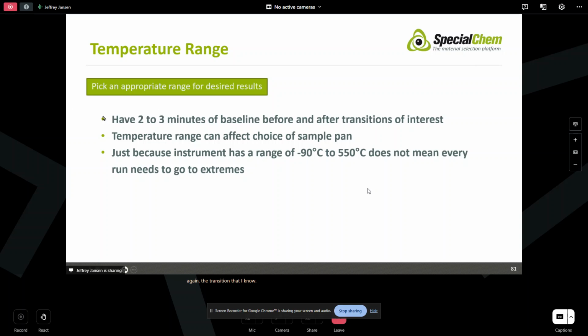One thing that you want to do in picking the low side temperature: the drawback of starting at room temperature is that transitions that are relatively low, maybe 40 degrees C, 50 degrees C, kind of get lost. You want 2 to 3 minutes of baseline before and after transitions of interest. So you want to have enough baseline, particularly on the low end side, because you get what's called a startup hook sometimes in the DSC. So again, choose that wisely.